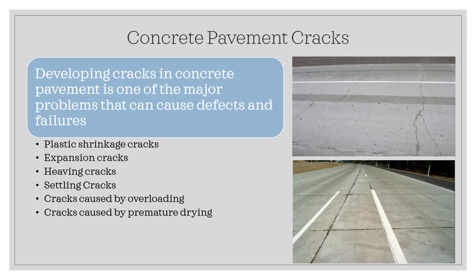The other type of crack is heaving cracks. When the ground freezes, it can sometimes lift many inches before thawing and settling back down. This ground movement brought on by the freezing and thawing cycle is a huge factor contributing to concrete cracking. If the slab is not free to move with the ground, the slab will crack. The other type of crack is settling concrete crack. Ground settling below a concrete slab can cause cracking.